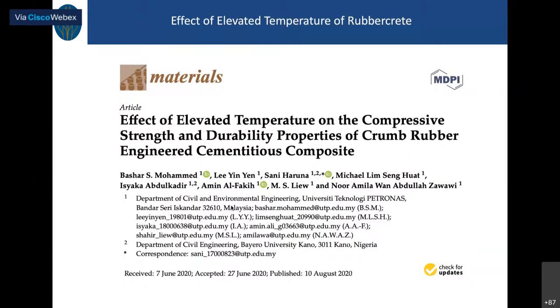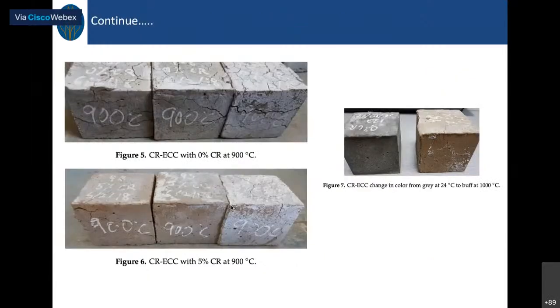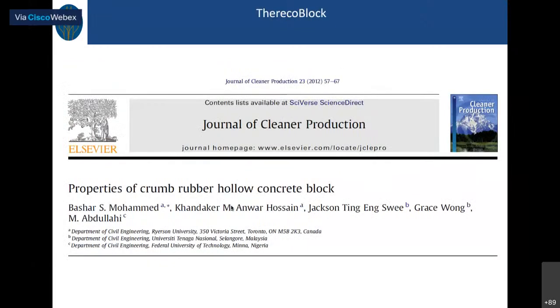And also, there is a big question: how does rubbercrete behave under elevated temperatures? Some people claim it catches fire, but actually it does not catch fire. We tested up to 900 centigrade, where we see that the compressive strength decreased, but there is no huge amount of CO2 or fumes or smoke after we burn it, because the amount we use is small and encapsulated inside the concrete.